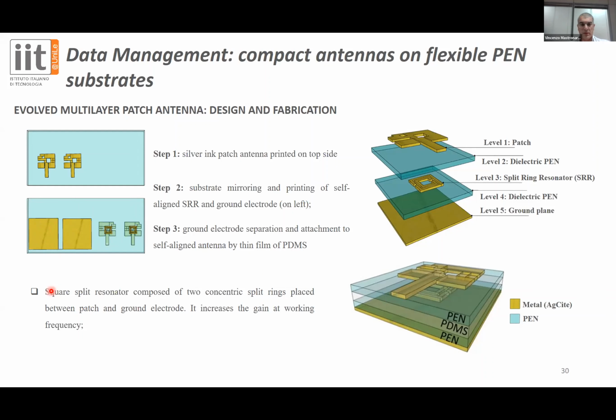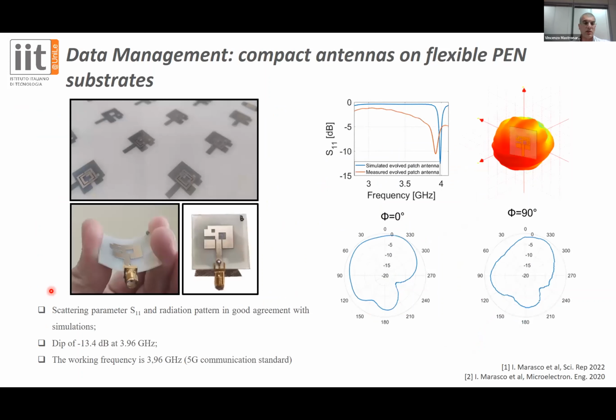Then the ground electrode is cut from the substrate, and it is attached on the bottom side of the antenna by using a very thin layer of polydimethylsiloxane, a material that acts just as adhesion material. So we tested these antennas again to see the performance in terms of transmission and radiation patterns, and as you can see from these plots, we have good agreement with the simulated antennas, with the main resonating peak at about 4 gigahertz. Again, we achieved a very thin and very flexible antenna, and again the silver ink still remains attached to the patch, even if it is folded or bent.